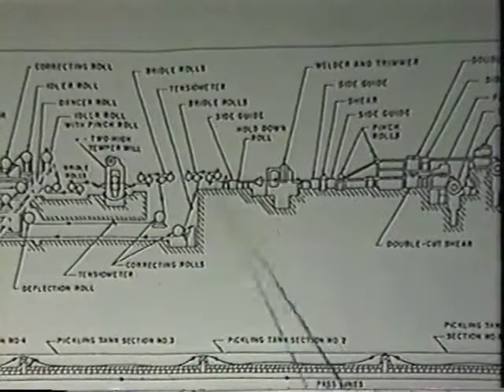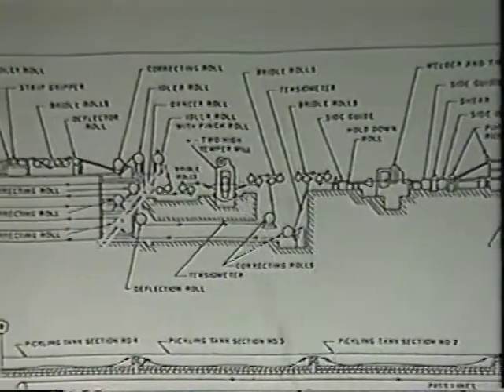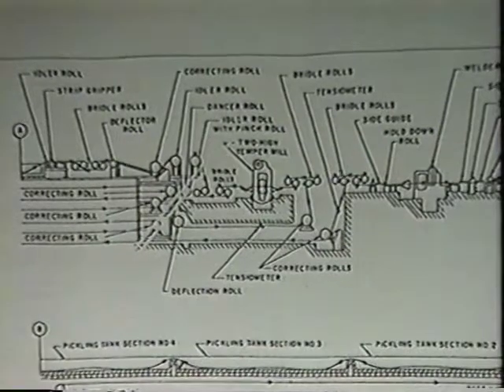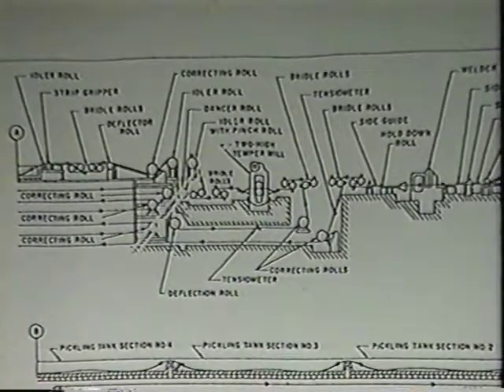We join the coils, we pull it through, and then it goes through a cold reduction mill. The cold reduction mill we call a bliss mill. It's meant to give the steel a small reduction, of anywhere between 1 to 2%. The purpose of that reduction is to break the scale. Scale, or iron oxide, is very brittle. It does not stretch. Steel, hot roll steel, does stretch. So if you reduce the steel a little bit, 1 to 2%, you're going to stretch the steel and it's going to crack the scale.